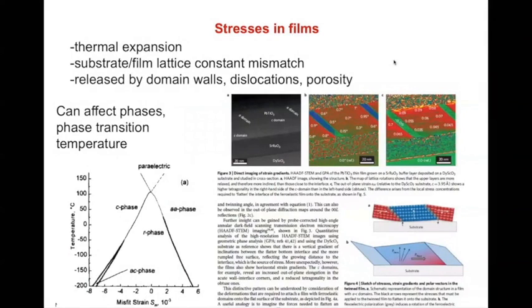When you make a film on a substrate, because of the thermal mismatch between substrate and sample, there will be a lot of stresses. If your material is ferroelectric, it will develop into domains to release some of those stresses. The stress in general will be inhomogeneous, as illustrated here — these non-homogeneous strains in the films can be very large, in the hundreds of megapascals.